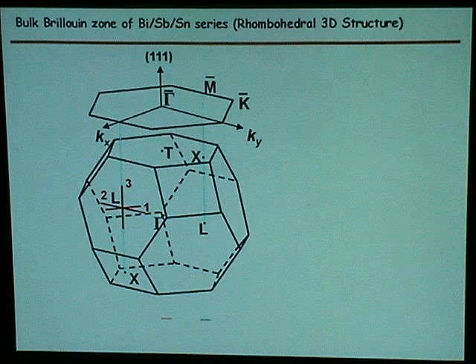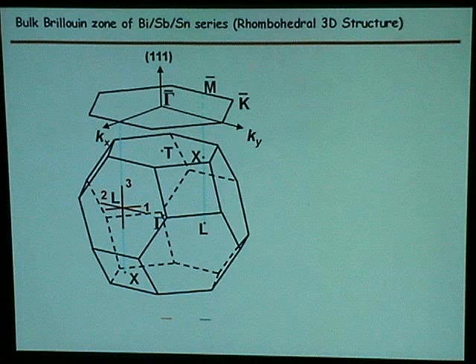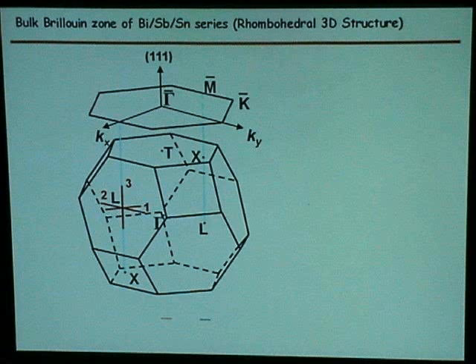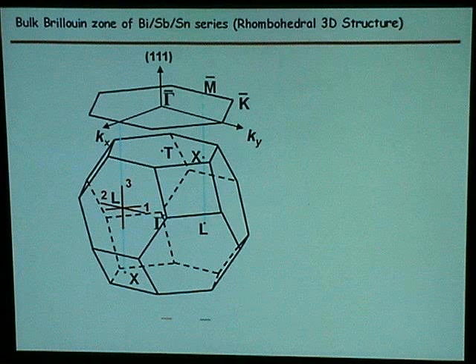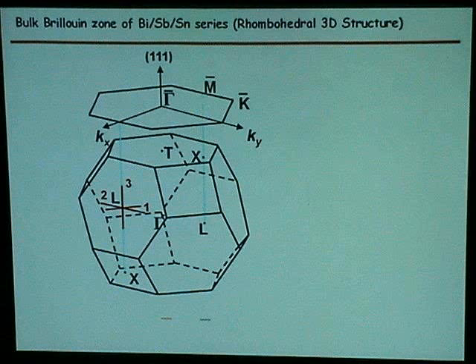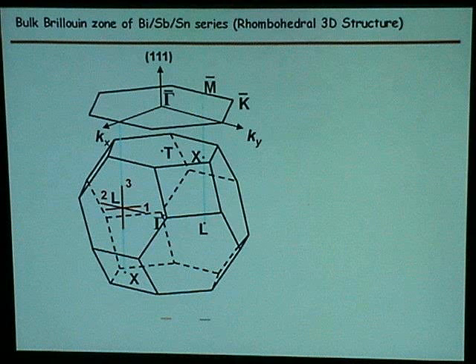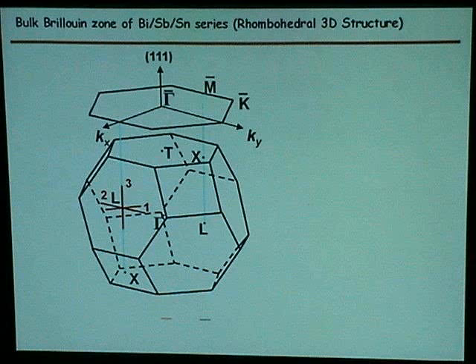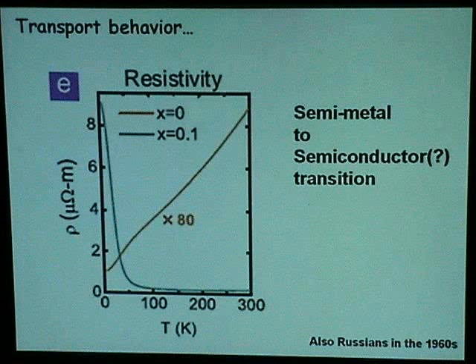Yeah. So you jumped ahead in my case, but it helped my point: if I measure the carrier concentration on the surface, as pointed out, it's very large. So you cannot get fractional quantum Hall effect from this surface at this concentration. So I ruled out that the 111 surface is responsible for creating the fractional quantum Hall effect in bismuth. But then I cannot do more than that. But I found something more interesting. Now I'm off fractional quantum Hall effect, but I found some other quantum Hall effect.